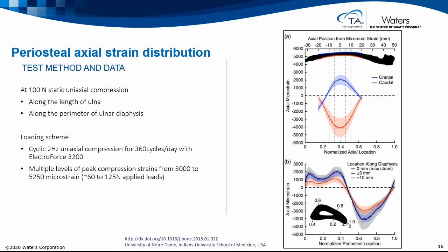And just to note, this 3,000 to 5,000 microstrain isn't an extreme amount of strain. I think the paper references that typical sort of moving around, running around is in this sort of 3,000 to 4,000 range. So it's not an extreme amount of loading. They're not failing these ulnar bones. They're just precisely applying force so that they can then more precisely understand the consequence of that force.